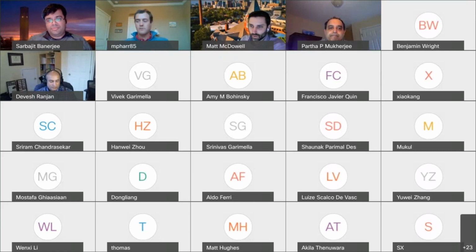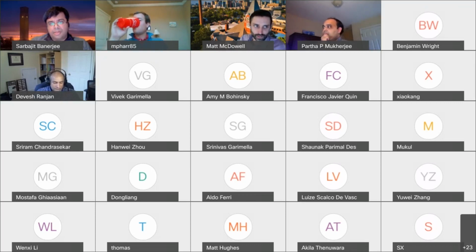Yeah, good question. If you remember back to that video, I showed you the reaction process between that single little particle and lithium metal. That's actually different than what we want. We want there to be no reaction, but I didn't really get into the details here. Virtually all solid electrolyte materials do show a reaction. But the transport of lithium ions through the solid electrolyte is a distinct process. That should happen without any volume change, because there's no change in the concentration. The reaction process to form an interphase is a different process that is actually a negative for your battery. You don't want it, but it's always there, basically.